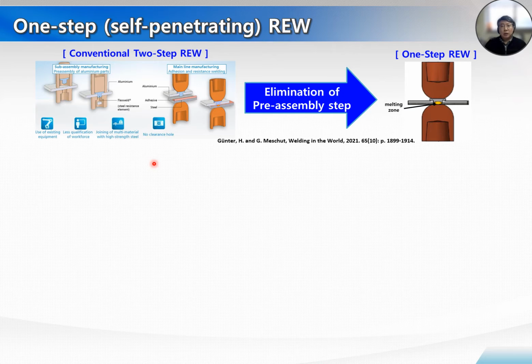Resistance element welding is a two-step process. The first is sub-assembly manufacturing, where the element is punched and inserted into the aluminum plates, and the second is mainline manufacturing, where the element and lower steel plate are resistance welded. However, in these two steps, it is difficult for a robot to find the exact location of the elements in mainline manufacturing, and the possibility of weld defects increases.